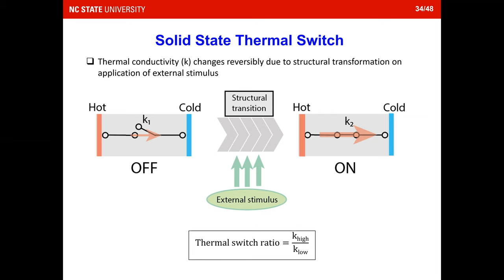Say if you want at this time the temperature to be higher, for example, the battery in the car, you can put on a very low thermal conductivity. But if you want to dissipate the heat, then you want to switch to a high thermal conductivity so the temperature can be cooled down really fast. So a very important figure of merit for this is called the thermal switching ratio, which is how large the contrast is between high and low thermal conductivity.